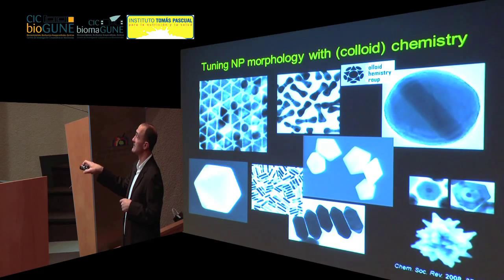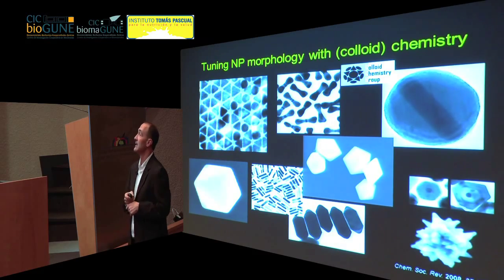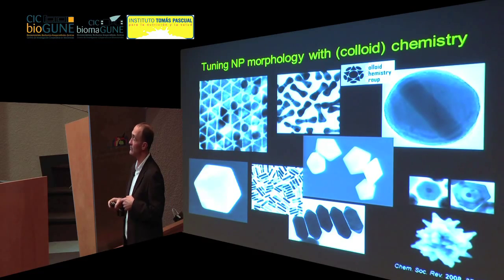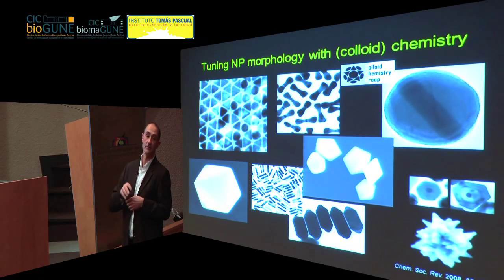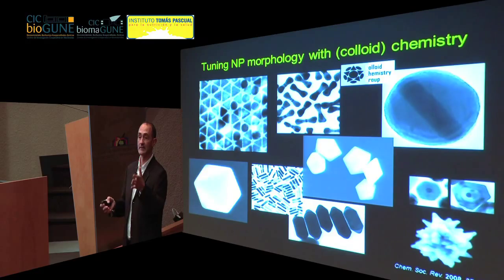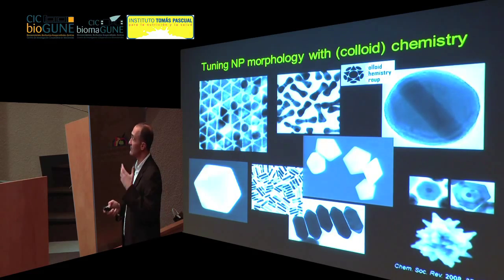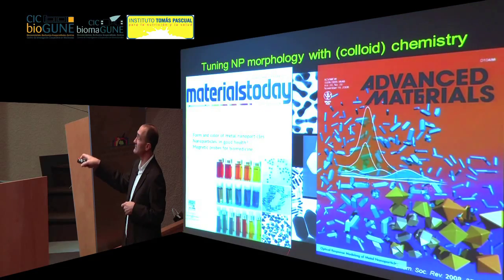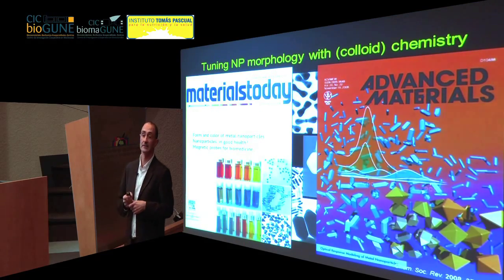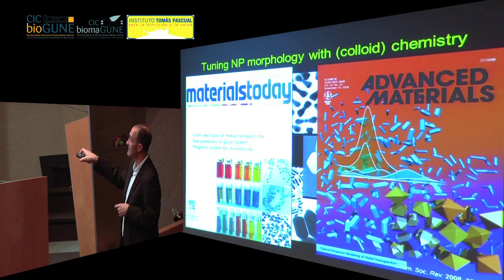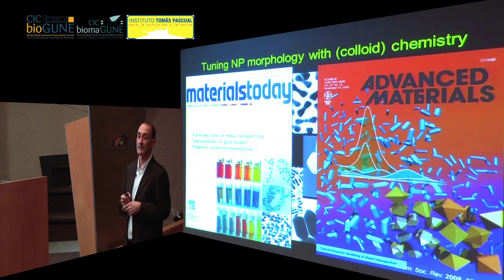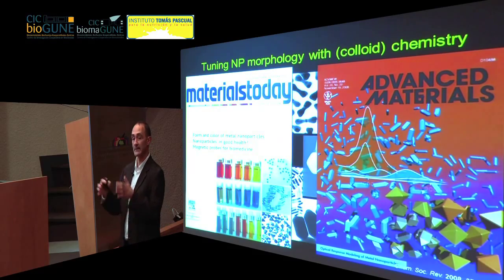All these pictures correspond to particles that we have made, basically made of gold or silver, and we are trying to understand how, by playing with the surface chemistry, we can direct the growth of certain crystalline facets while others do not grow. This is the only way to control the morphology of the materials. We also analyzed the effect of all these morphological changes on the colors of the solutions of these particles. And then through theoretical methods, we could also understand and correlate the experimental observations with the theoretical predictions.